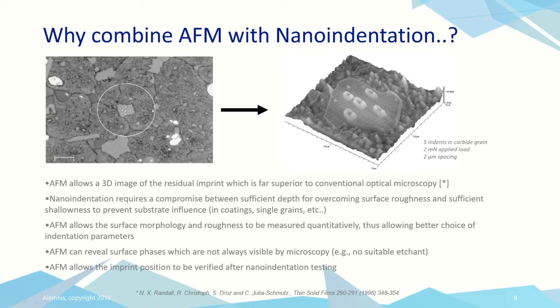Now, you can see here on the left image, we're looking at a grain in a microstructure. This grain is about 10 microns across, and this is the limit of optical microscopy. This is 1,000 times magnification. And the indents here are made with a 2 millinewton load, and they're basically dots on the surface.